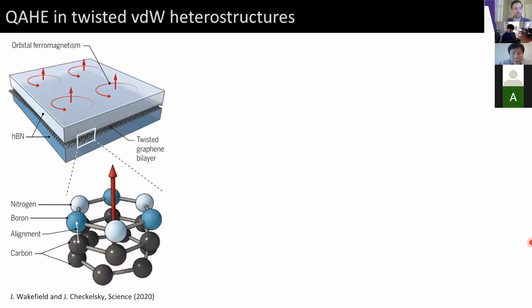And what's interesting about this quantum anomalous Hall effect is that it's completely orbitally driven. So normally, quantum anomalous Hall effect requires some sort of explicit time reversal symmetry breaking, for example, in some sort of magnetically doped topological insulator. In this case, there's no explicit time reversal symmetry breaking. We're just measuring graphene, it's just carbon, and so the spin-orbit coupling is extremely weak, and there's no explicit magnetic dopants.